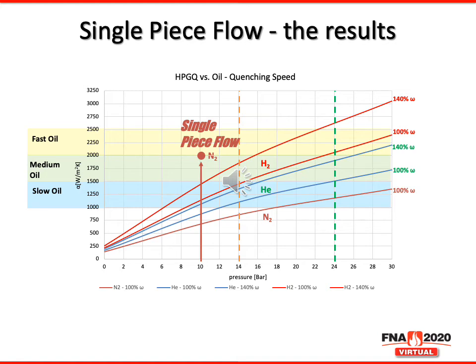Next question is, what is the effect? Well, as you see from this chart, the net effect is fairly strong. As you'll see here, we have data from a high pressure gas quench furnace where the parts are inserted in a batch into a quenching chamber. So this isn't just a single chamber furnace, it's a two-chamber furnace, and the second chamber is for quenching only. You'll see too that the gases are varied from nitrogen to helium to even hydrogen, and the pressures are varied as well along the horizontal axis.